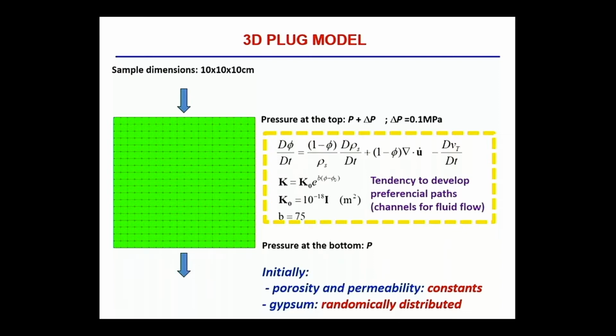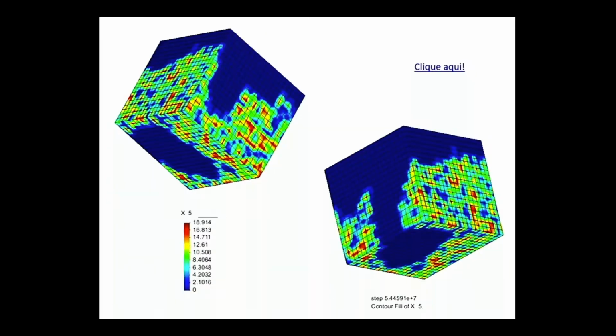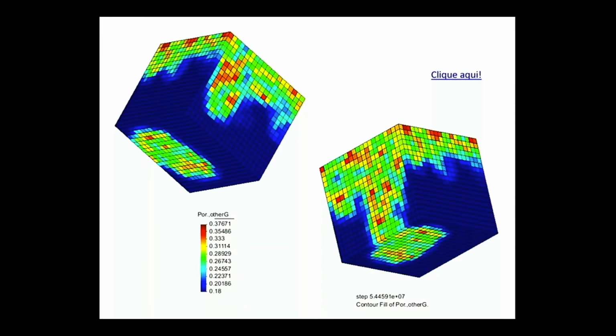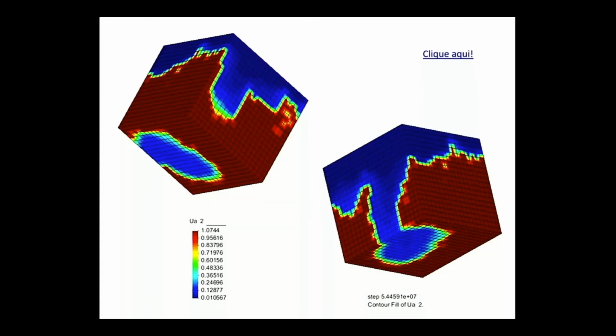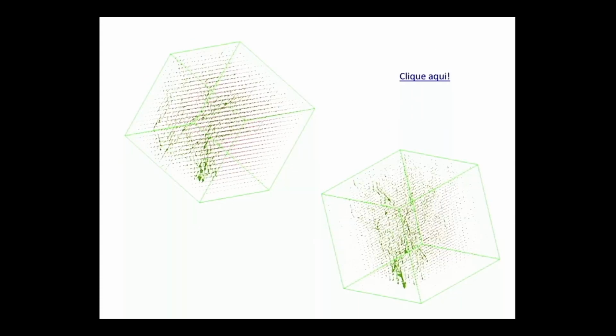And in fact, here in the sample, this is the dissolution of mineral. You can see that for higher flow injection, we can see the wormhole forming. This is the zero concentration of mineral here. The reactive mineral disappears here. You can see higher porosity where the mineral disappears. Okay, this is the concentration of injected fluid. This is the blue one, the injected fluid, and the flow is concentrated in this high permeability channel.